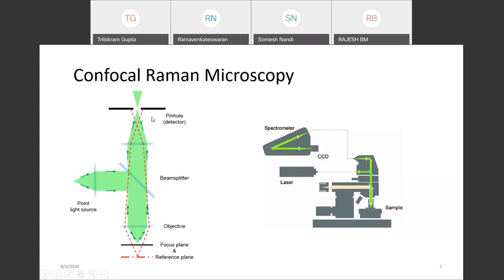After the signal is collected on a CCD detector, the spectrum is created on the spectrometer. Depth profiling with confocal Raman spectroscopy can be applied in two ways: the first approach plots the intensity of a specific band as a function of distance from the sample surface, providing information about composition or structure gradient of the sample. The second approach acquires a full spectrum of a varied structure. Either dispersive or non-dispersive spectrometers are used — a prism or a grating. A grating is employed in the dispersive spectrometer, whereas a non-dispersive spectrometer employs an interferometer analogous to the Michelson interferometer used in FTIR.